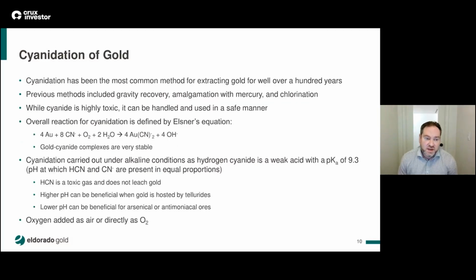Moving on to cyanidation. Cyanidation has been the most common method for extracting gold for the last century. Previously, gravity recovery, amalgamation with mercury, and chlorination were very common, but these have mostly been replaced. While cyanide is highly toxic, it can be handled and used in a safe manner. Looking at the overall reaction for gold cyanidation, we require oxygen to be able to produce the gold cyanide complex, which is a very stable leaching product.